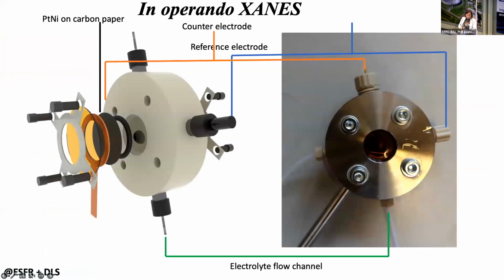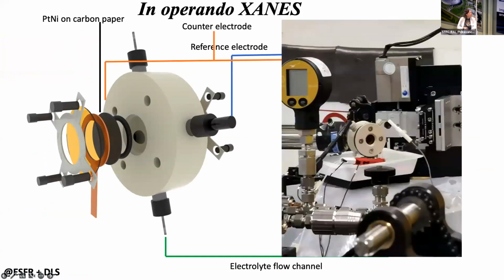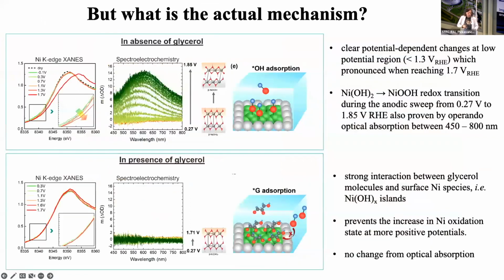Now we went and did some in operando XAS, both at Diamond and ESRF. And this is our cell where we have our platinum nickel on carbon paper, our working electrode, and we have our reference and counter electrode, and we could do this in operando. And again, we did this in the absence of glycerol, and we could see that the spectra change quite a lot. We suggest that the nickel is indeed oxidized.